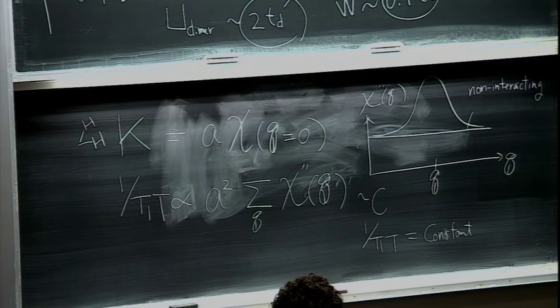The difference is only in the amplitude of the coupling constant, but the important point is the temperature dependence. So it does not matter - the two carbon sites show nearly exactly the same temperature dependence.